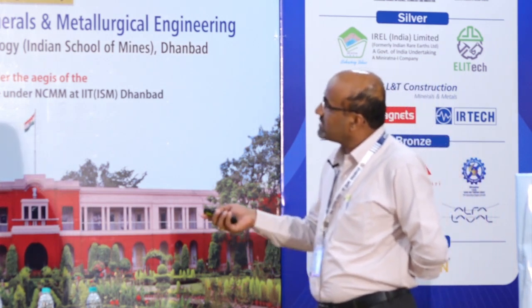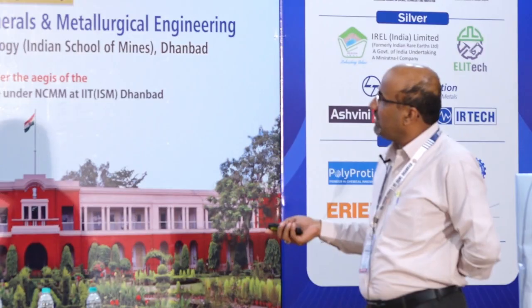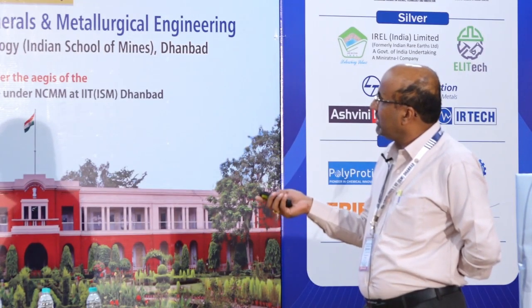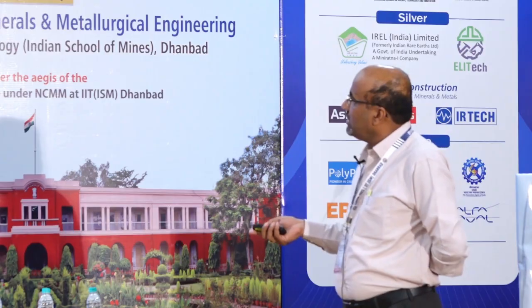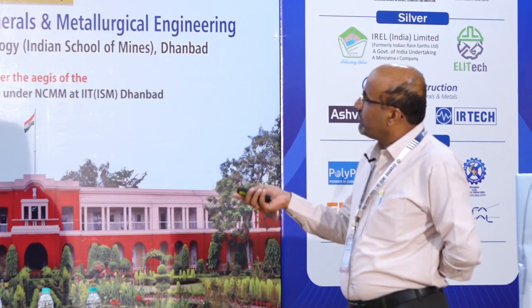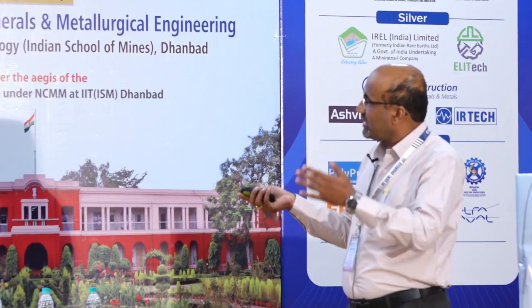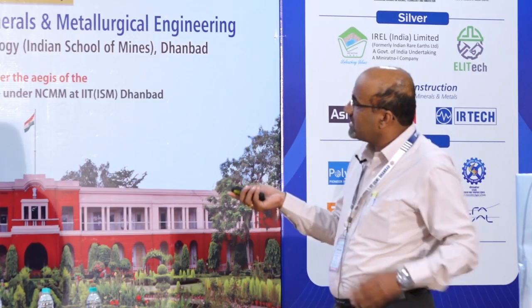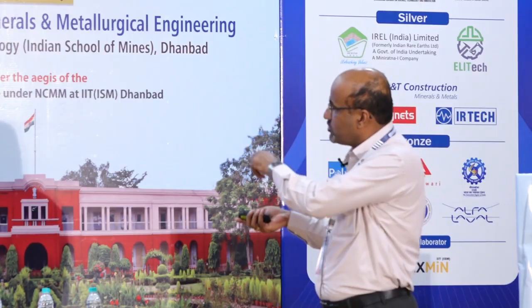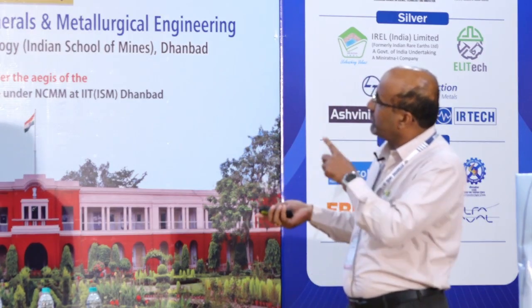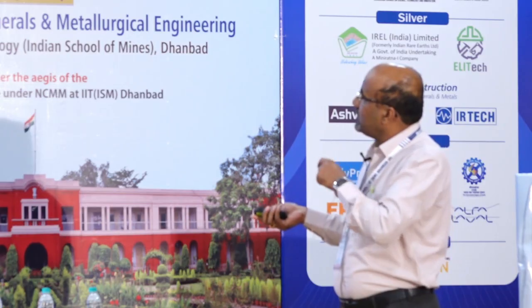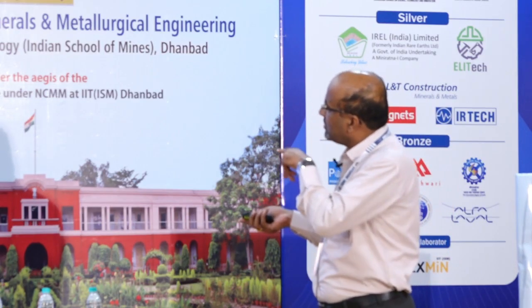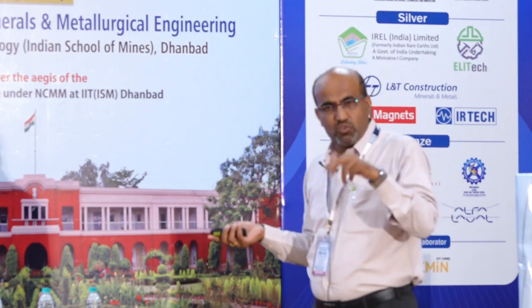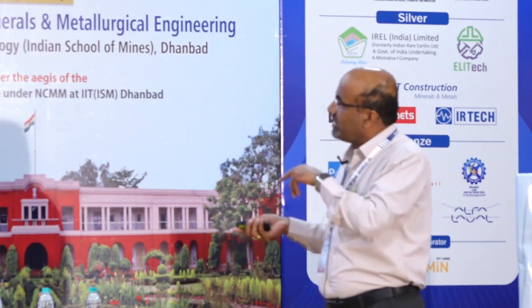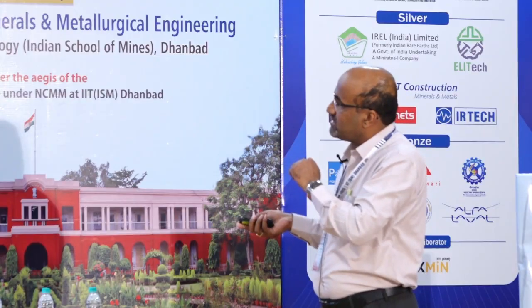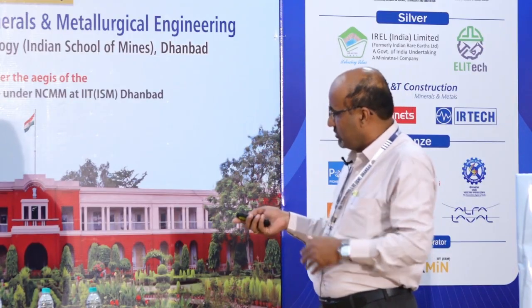This is how to do it. This is the DFT optimized geometry. I have taken only four elements: lanthanum, yttrium, europium, and lutetium. If you see the bond distances from lanthanum onwards, because of the lanthanide contraction, until lutetium the bond distances with the ligand become shorter. The beauty is that in the case of yttrium, an additional water, which is not shown here, comes into the picture, and because of that hydrated water, the yttrium remains in the aqueous phase, even the lanthanum remains in the aqueous phase, while only the heavy rare earths go to the organic phase.